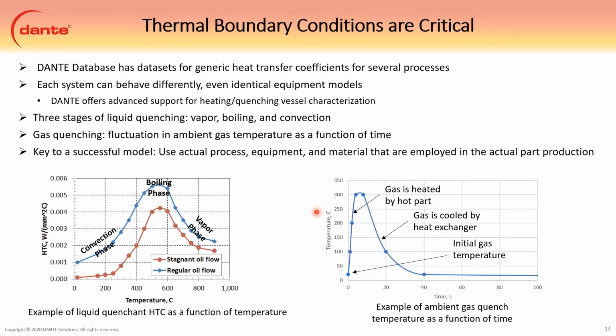And the key to all of this is you want to test your actual process route. So make sure that your temperatures and your times are representative of your process. You want to use the equipment that you're using. Testing fluid in a beaker in a lab is good for quality control. It's not good for heat treatment modeling. It'll help, but it's not what you really want. What you really want is your actual equipment, and then obviously the actual material that you're using.